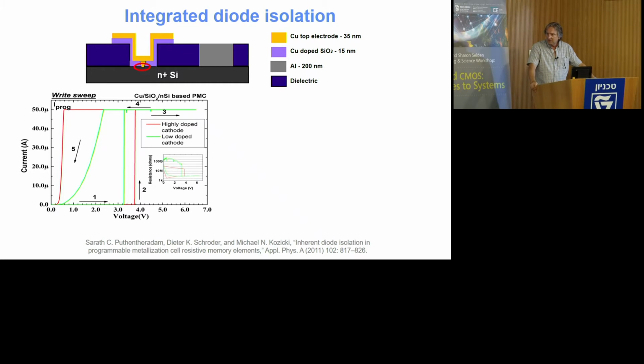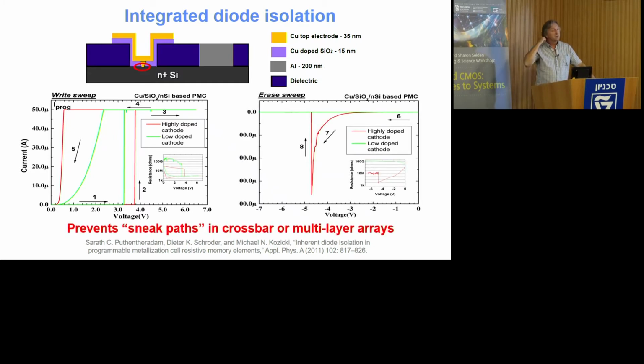And we were able to do that just literally by growing a copper filament on top of the N plus silicon, showing here in the green and red curves for two different doping levels in the silicon. Basically, it's a Zener diode. Now, of course, because this is a bipolar device, it requires negative voltage to switch the thing off. It's important that that diode was Zener-like and had a negative breakdown, and indeed, in the highly doped silicon case, we did get that negative breakdown, allowing us to switch these devices off. In the lightly doped case, we don't get the breakdown as you might expect, and the reverse current is blocked. So, good for one-time programming things, but not for reprogrammability.